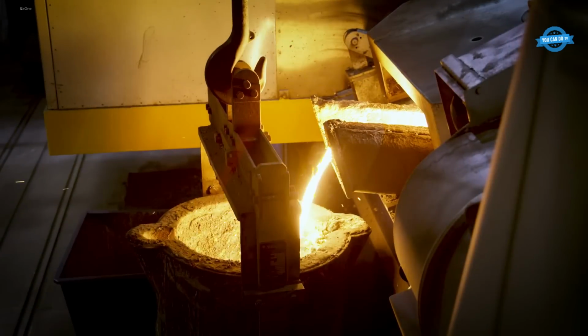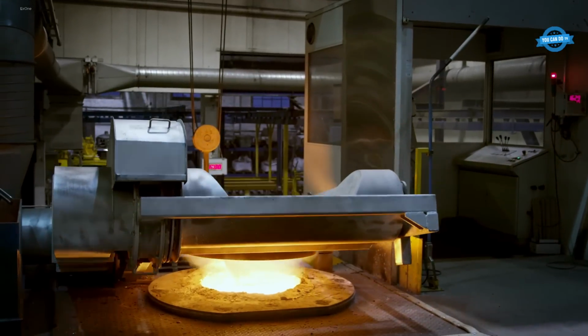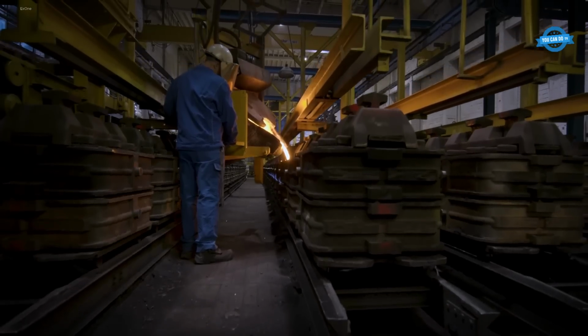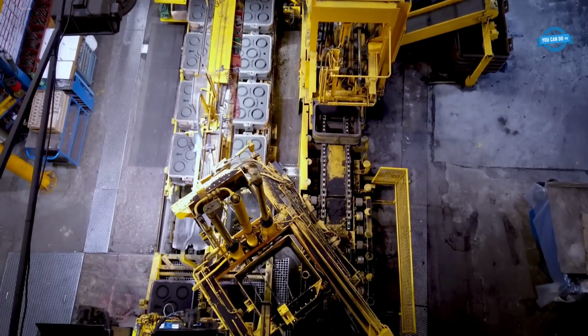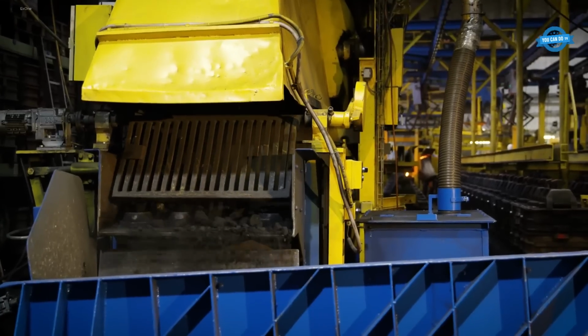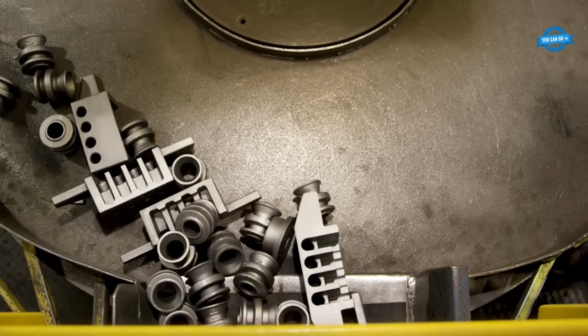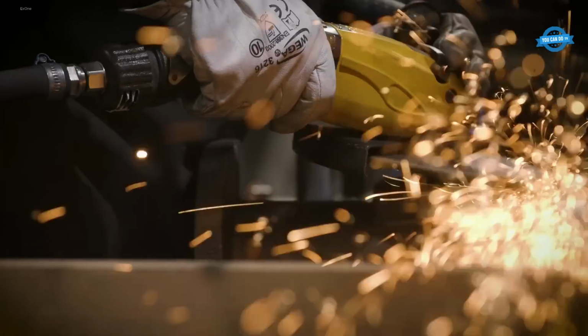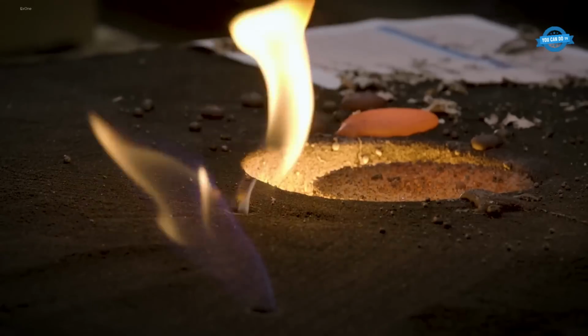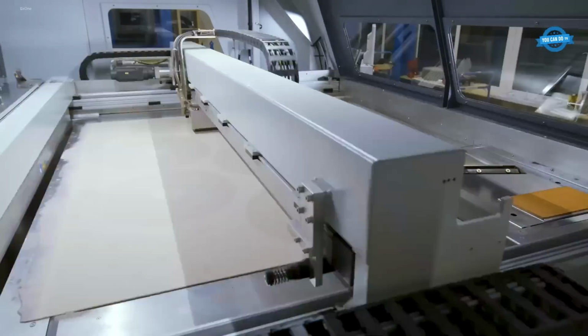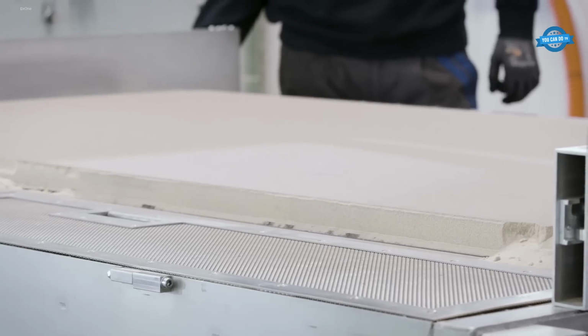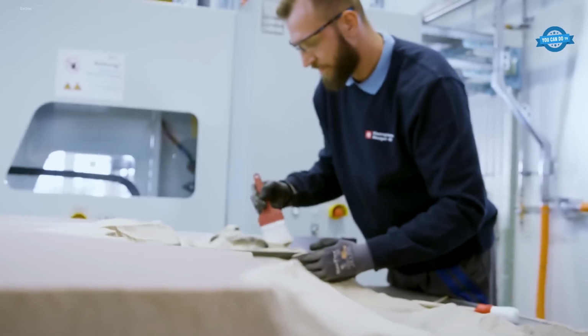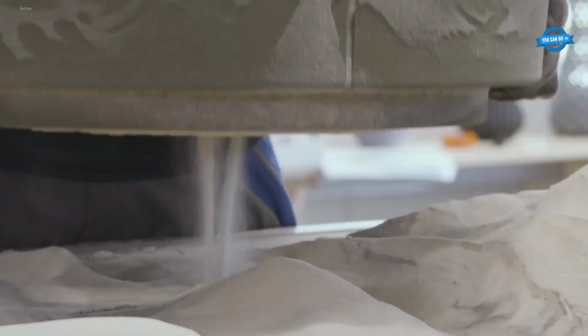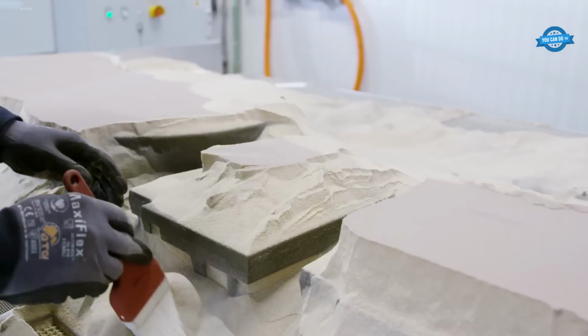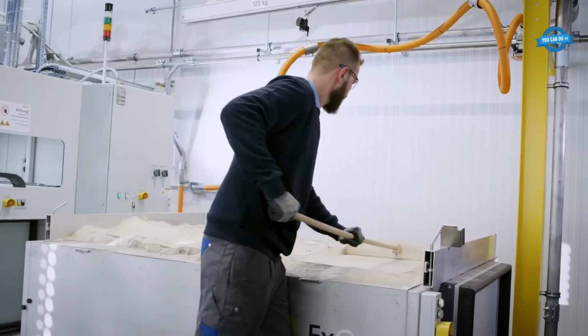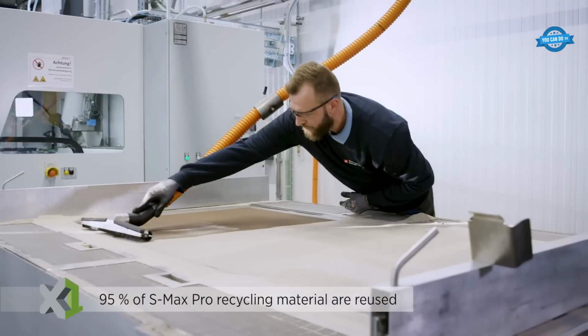The Foundry integrates X1 3D printing technology to modernize and enhance production. The X1 system enables high-precision mold production with complex geometries and minimal material waste. A semi-automated desanding station efficiently recycles unbonded sand with up to 95% reuse and mixing ratios of 80% regenerate. The system operates 24/7 with high reliability. Printed molds emerge nearly dust-free, requiring only light finishing.